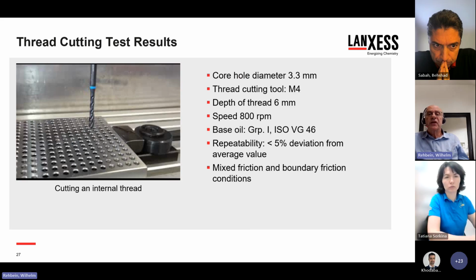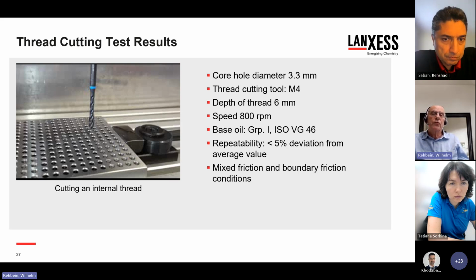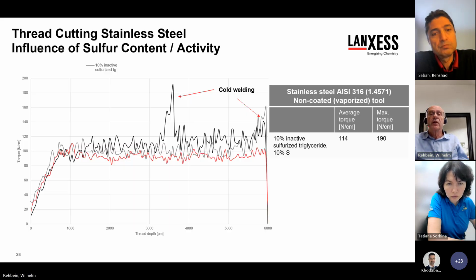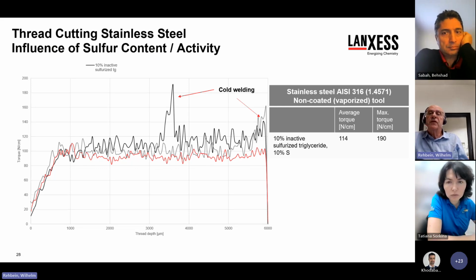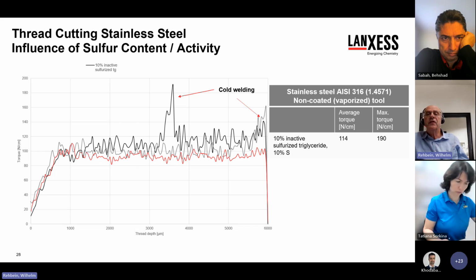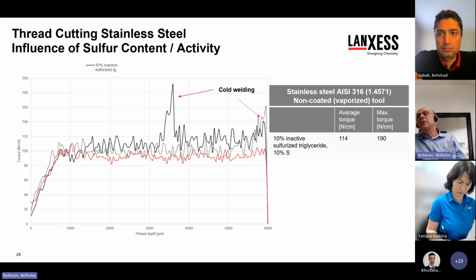I would like to start with our thread cutting test results. The diameter of the core holes was always 3.3 millimeter. We used an M4 thread cutting tool. The depth of the thread was 6 millimeter. The speed was 800 RPM, and we always used the Group 1 ISO VG 46 base oil for our tests. First of all, we did the thread cutting in AISI 316 stainless steel, because contrary to normal steel, the surface of stainless steel is nearly completely covered with metal oxides, which makes it quite difficult for EP additives to interact with this surface. And it's also difficult for metalworking fluid to perform well with stainless steels.